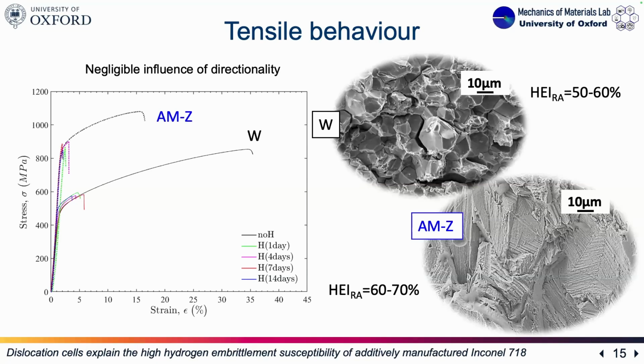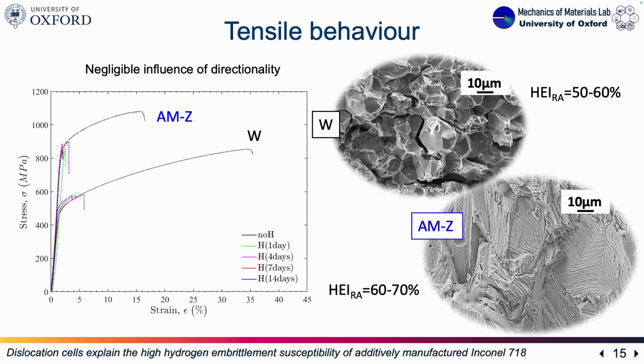And regarding the fracture surfaces, we see no effect of directionality, again like what happened in the TDS analysis. So not a lot of difference between having the sample in one direction or the other regarding the building direction of the print. Okay, and we have intergranular fracture for the rod, and then we have some kind of weird transgranular fracture for the additive that resembles these cellular structures that we could see in the previous slides in the microstructure. So we can infer that here we are having decohesion along these dendrite interfaces.